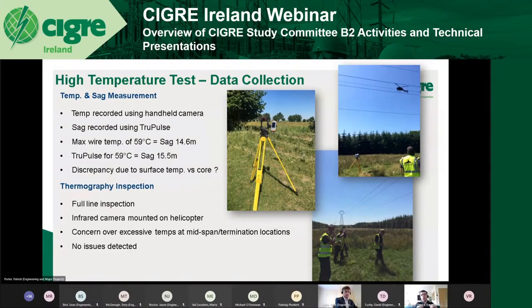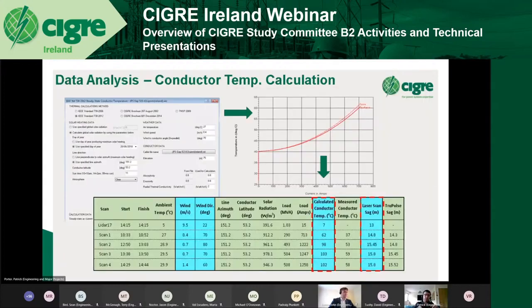And finally, then, a thermography inspection. So in addition to the handheld camera, there was a full line inspection done via helicopter, as you can see in the top right-hand side there. That's just an infrared camera mounted in the front of the helicopter, and it flies through the line and carries out that inspection. The reason for that is that if you have a line operating under a period of sustained high loading, in this case 4 hours, any locations on the line that maybe are showing increased levels of fatigue, so things like mid-span joints, termination locations, etc., would make themselves known during the high loading period. So that was the reason for that, but thankfully there were no issues detected.